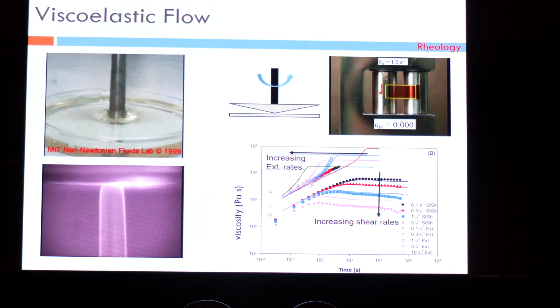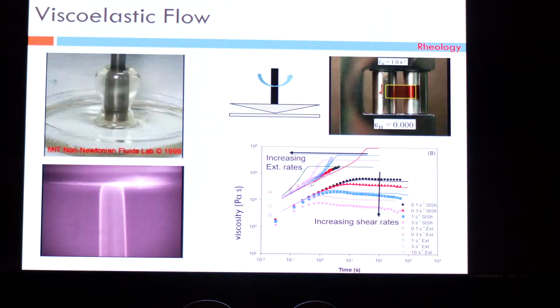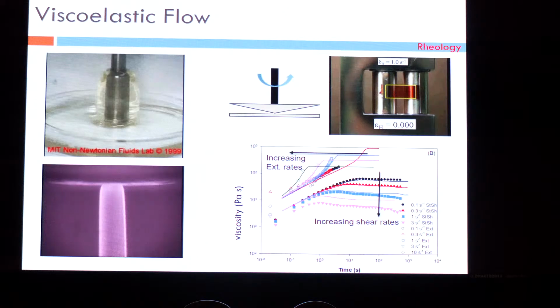And you will see that the first thing that these molecular structures, these long chain structures do, is they give very interesting properties for flowing, for the flow behavior of these polymers. So on the top you will see a polymeric liquid in which you are simply stirring a rod, and instead of forming a vortex which pulls the liquid down, which is what we normally see in our chemistry wet labs, you take a polymer, it actually rises on top of this rod. It's called the rod climbing effect. And this is very unusual. The polymer is actually fighting gravity and going in the direction opposite to the gravity.